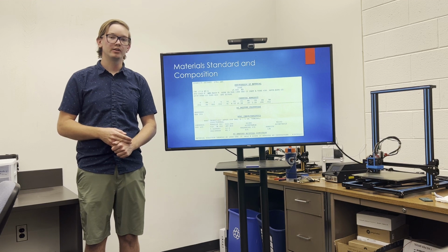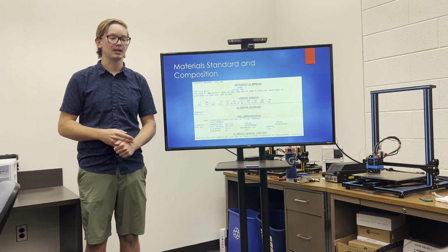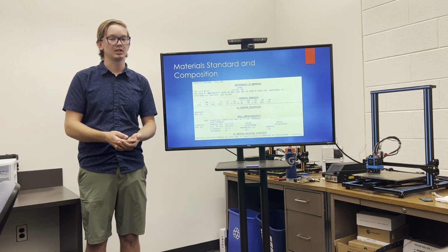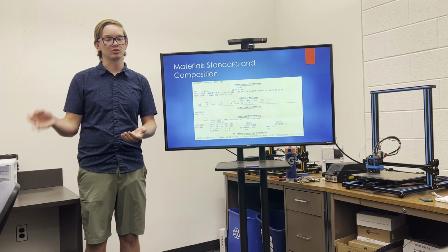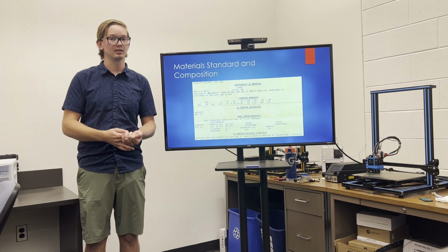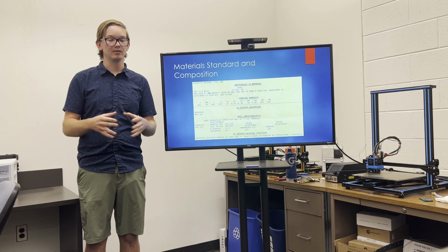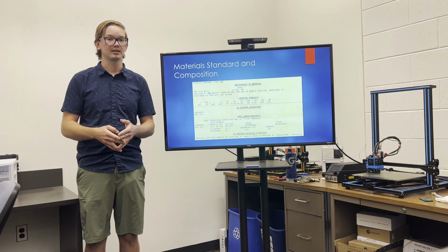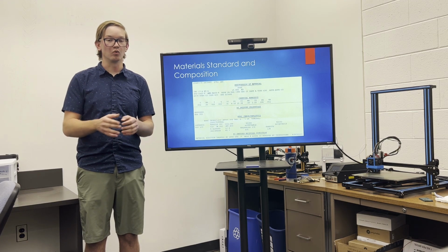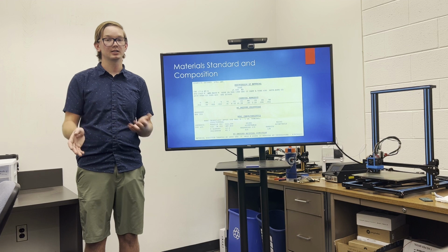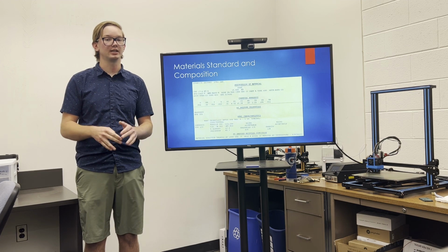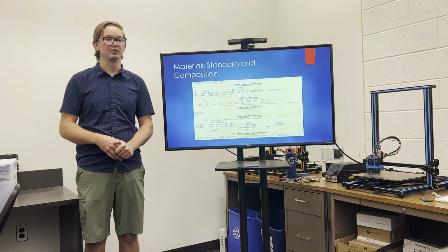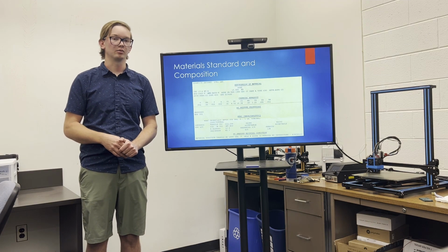The trouble with using the material in condition A, it's softer that way, so easier to machine, so typically it's provided in that condition and then expected to be treated to H900. It can't be used in condition A typically because uneven precipitation during that long heat up and slow cool process can cause irregularities throughout the billet that can lead to unexpected brittle fracture, as well as varying yield strengths that can lead to unexpected ductile rupture.